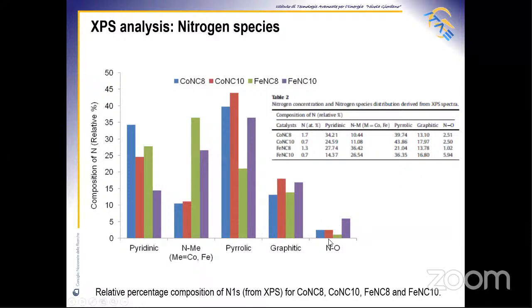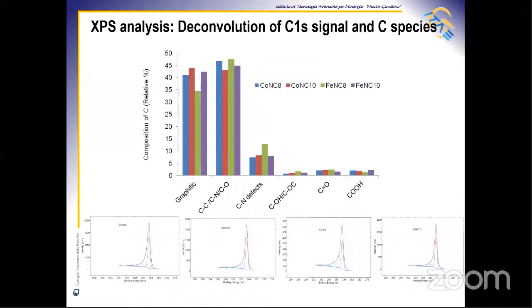One of the most important data reported here is the strong interaction between nitrogen and iron atoms, probably due to the higher formation constant of the complex compared to cobalt EDTA formation. FeNC8 exhibits also the smallest amount of pyrrolic nitrogen species. Furthermore, this figure shows the behavior of the different metal nitrogen carbon compounds towards the carbon 1s composition. It results that FeNC8 has a smaller relative amount of graphitic carbon and the largest number of carbon-nitrogen defects.